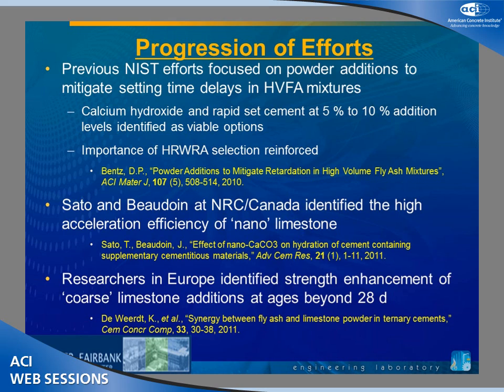Then just a little beyond that, there was information coming out of NRC Canada, Tai Sato and Jim Baudouin. They were showing that you could really accelerate cement systems, pure Portland, or even with supplementary cementitious materials using nano limestone. So these are limestone particles that are on the order of, say, 50 to 100 nanometers.